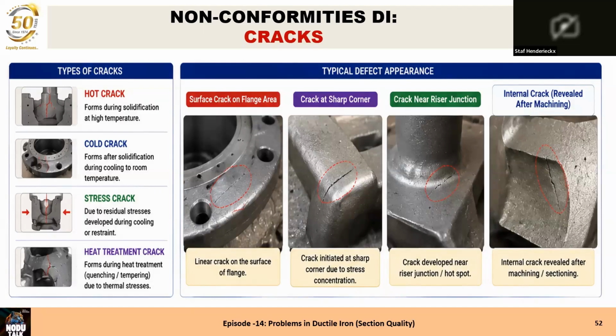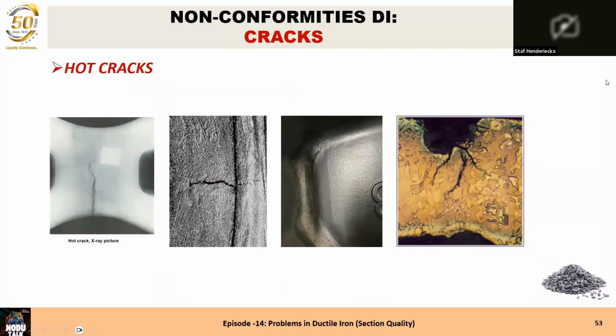The same with the third casting near a riser junction. There it's mostly a hot crack that you have, and an internal crack, as you see at the right side after machining, that has always to do with the defect, mostly porosity, which is inside the casting, and then during the solidification it acts as a crack initiator, and it's due to the stress. You can see on the left side that's a hot crack X-ray picture. The second is a hot crack seen on the casting itself. The third one also, and fourth one also, and that's due to defects. The fourth one, the right one, is due to defects, so that it cracks to the outside.